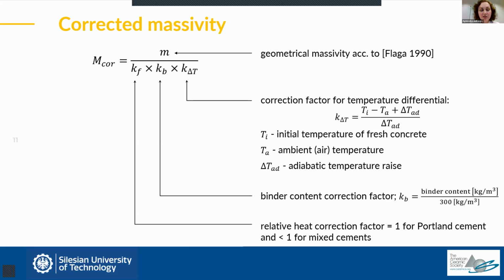So eventually, how do we interpret this corrected massivity? We interpret it in such a way that if the value of this massivity factor is higher, it means that the structure is less prone to thermal cracking. And we have defined that if this massivity is below 2, then such a structure can be classified as massive, which means that it's susceptible to thermal cracking. And if it is above 2 and between 2 and more or less 15, then such a structure is medium thick, which means that thermal cracking potential is non-negligible.